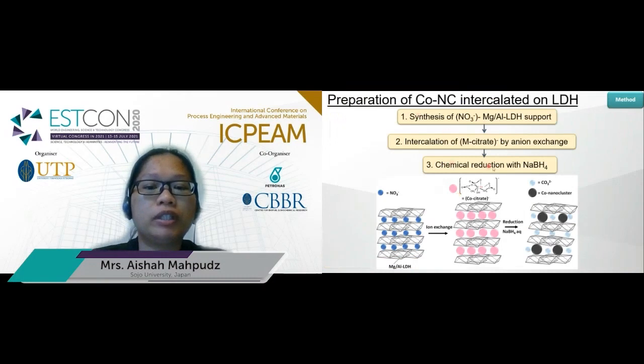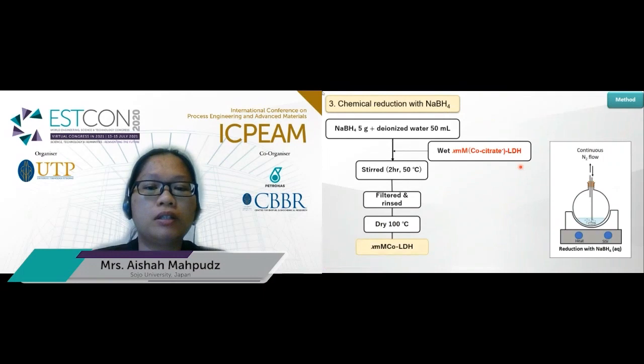So for the chemical reduction with sodium borohydride, 5 grams of sodium borohydride is added to 50 ml of water. Then the wet X millimolar cobalt citrate LDH is added. This whole solution is stirred for 2 hours at 50 degrees Celsius. It is then filtered, rinsed and dried at 100 degrees Celsius. And I refer to the sample as X millimolar cobalt LDH, whereby X refers to 4, 2, 1, and 0.5 millimolar